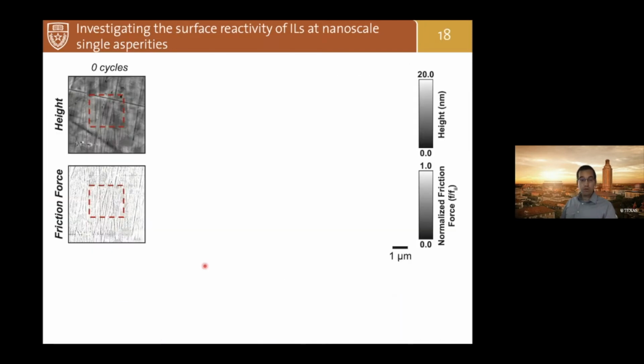So let me go to some of the results. At the top, you see the topography image, and at the bottom, the friction image, which is acquired at the same time with our AFM instrument. The dark red dashed area that you see here is where we increase the load to the maximum load that we can achieve with our AFM.